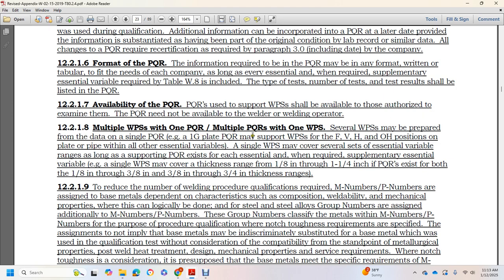One G-plate procedure qualification may support a welding procedure specification for flat, vertical, horizontal, and overhead positions on plate and pipe, with all the other essential variables. A single welding procedure specification may cover a range of essential variables, as long as the supporting procedure qualification record covers each essential and required supplemental essential variable. A single welding procedure specification may cover a thickness range of 1/8 to 1 1/4 inch if the procedure qualification record exists for both the 1/8 through 3/8 inch and the 3/8 inch to 3/4 inch ranges.